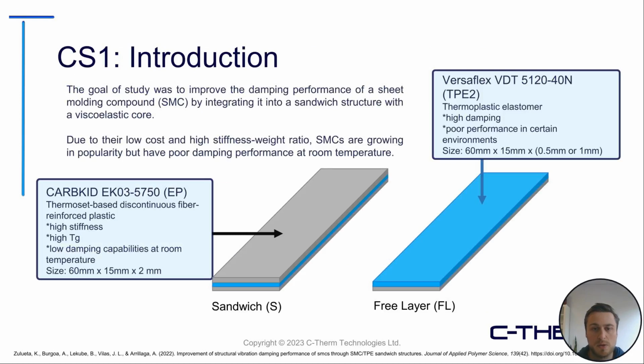The goal of this study was to improve the damping performance of a sheet molding compound, or SMC, by integrating it into a sandwich structure with a viscoelastic core. Due to their low cost and high weight stiffness ratio, SMCs are growing in popularity but have poor damping performance at room temperature. So this group was interested in seeing if they could improve the viscoelastic properties of the SMC by integrating a viscoelastic core, with the hopes of using it in vibration critical applications like EVs.